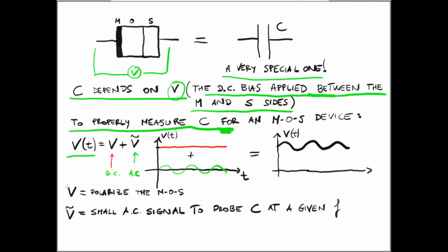So my DC signal is this one here in red, and my AC signal is this one here. Just for the formalism, when you see V, this means the DC voltage used to polarize the MOS device, while when you see V tilde, this means the small AC signal used to probe the capacitance at a given frequency. So effectively, when we are talking of MOS devices, we are always talking of signals applied to the device that have the shape that I've shown here. I would like to stress, we need a DC signal to polarize our device, either in accumulation, depletion, or inversion, and then we need an alternating signal to probe the capacitance in that situation.